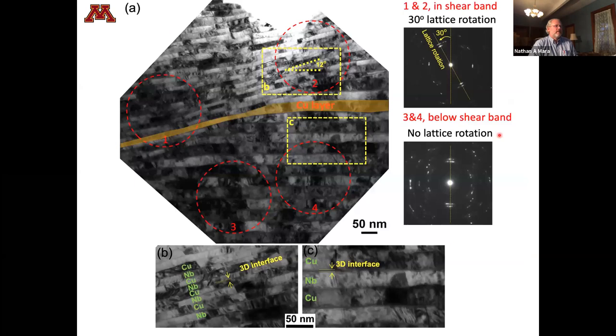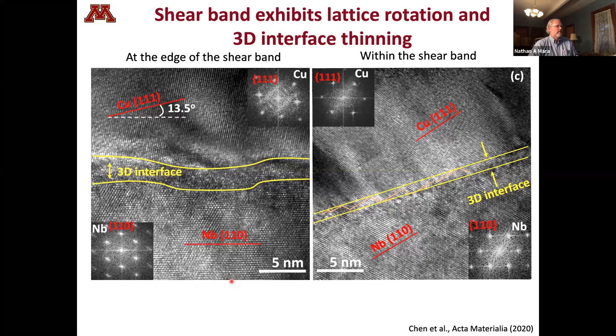Now what you see is you can see our copper layer. It thins gradually as you enter into the shear band. And you can look at different regions. We've looked at regions inside the shear band, outside the shear band, and so forth. And what we found is that after deformation within the shear band, you both thin and rotate the layers, but by a different process than what we've seen by PVD. The 3D interface still persists after we've deformed it. So you can see a 3D interface right here.